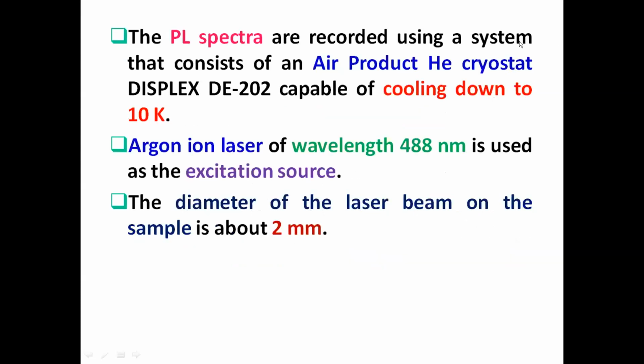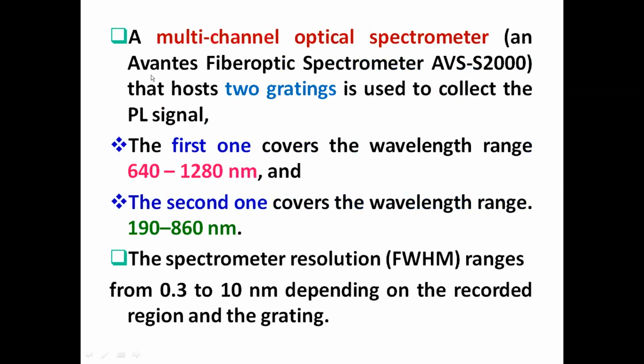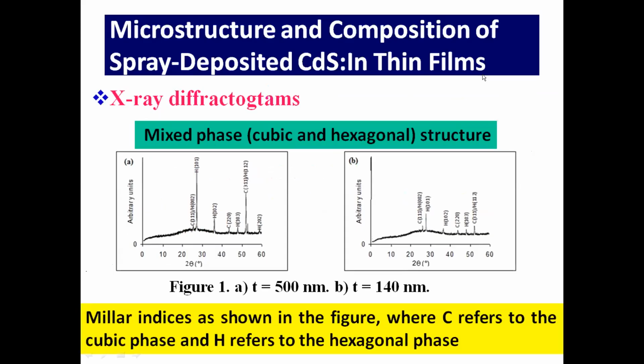PL spectra are recorded using an Air Products cryostat that enables cooling down to 10 Kelvin. An argon ion laser of wavelength 488 nanometer is used as the excitation source. A multi-channel optical spectrometer, Avantes fiber optic, is used to collect the laser signal and the PL signal, and it has two gratings. The first one covers the range 640 to 1280 nanometer, and the second grating covers the range 190 to 860 nanometer. Here are the results and discussion.